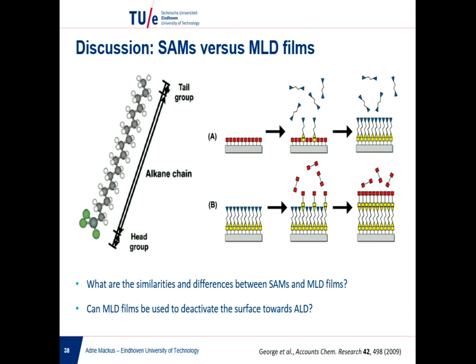If you think about making layers, coupling these MLD precursors until you have a certain length, I think this only works if it's a perfect layer. So if, for example, in your last step you're not completely in saturation, there might be some secondary reactions where you don't cap every monolayer, and of course every point where it's not perfect is a site where you can adsorb your precursor.